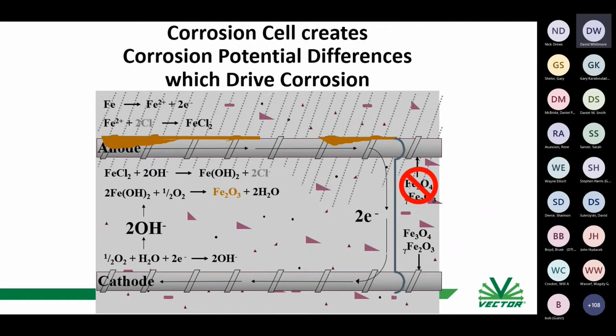If you go and do a corrosion potential survey, like Arnie mentioned early on, and you do a corrosion potential measurement of a piece of steel that's in chloride-free concrete or not carbonated concrete, you're typically going to measure a potential that may be around -200, maybe even a little more positive than that. Okay. If you measure the potential of the steel in chloride contaminated concrete, you're going to measure a more negative number. Okay. These numbers that I've put on the screen are simply picked from the ASTM standard for the method. You know, if you're -200 or more positive, the steel is typically considered passive or not corroding. If you're more negative than -350, the ASTM standard says that there's a high probability that corrosion is occurring.